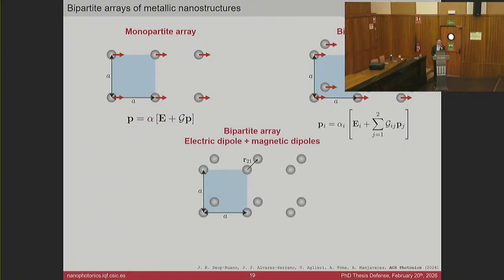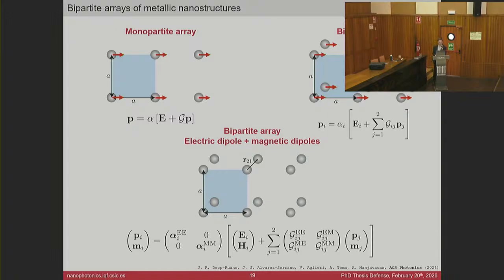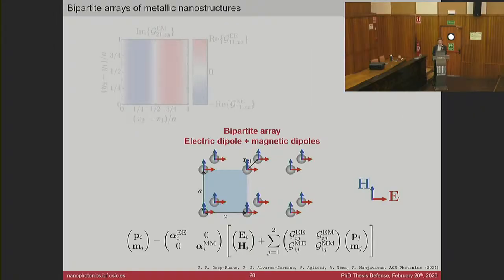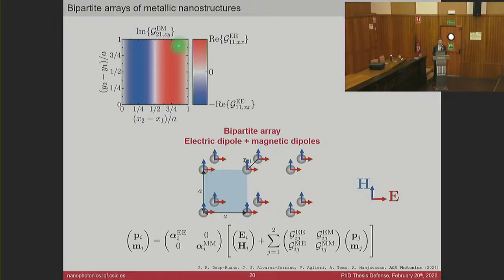Now, what I'm going to explore is a bit different, because not only do we have a bipartite array, but each nanostructure is modeled as an electric dipole and a magnetic dipole. And now we are going to consider the coupling between these electric and magnetic dipoles through these GEM terms, these electric magnetic interaction terms, because we are going to come with an electromagnetic field exciting both electric dipoles and magnetic dipoles. These electric magnetic coupling terms are going to be really interesting because they are able to couple in-plane and out-of-plane components. And this is exactly what we want: to come with an in-plane polarized electric field and excite an out-of-plane resonance.